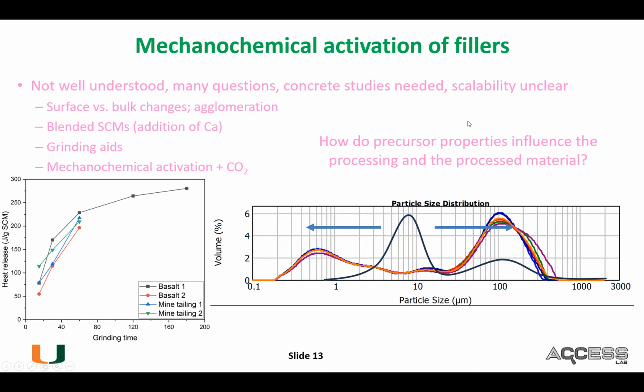It could be because you have almost some sort of sintering effect, because the temperatures do go high. Or, we've looked at the electron microscope, and what you see are large particles, but they're not that large. It seems to be a large particle with a bunch of small particles stuck to it, and then another large particle also stuck to it. Now, how easy or hard these particles are to disperse would have a major impact, because to a certain extent maybe that's exactly what you want: if initially that's the state of the particles, then you get an improvement in workability. But later on, if they dissolve, or the surface area is high enough, then we have an advantageous situation. In fact, in several of these cases, we've seen that the median particle size increases and the surface area increases at the same time. So there are some interesting synergies here that need to be solved.